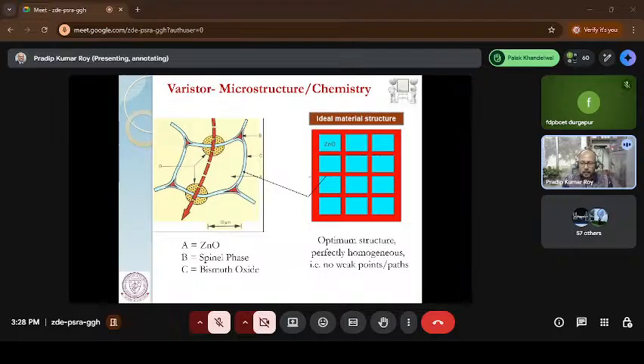So in general, if you look at the microstructure, this varistor is normally composed of three kinds of phases. One is the major zinc oxide phase. The zinc oxide phase is coated with the bismuth oxide phase, and at the triple junction of this bismuth oxide, there is a phase called the spinel phase. I'll talk about the composition part of the spinel phase later. So these three phases are there. This spinel phase actually controls the grain size, of both your bismuth as well as your zinc oxide.